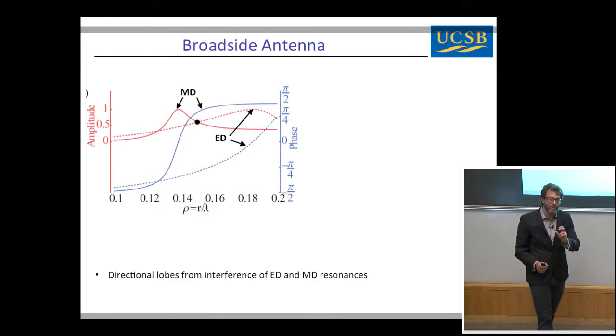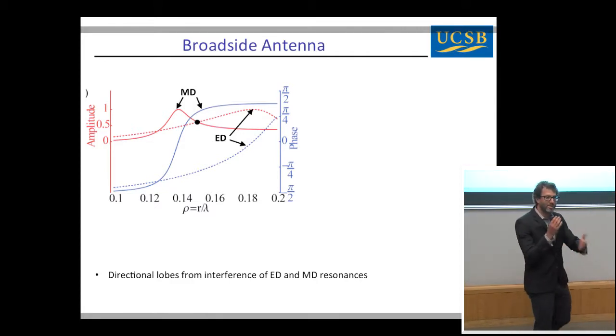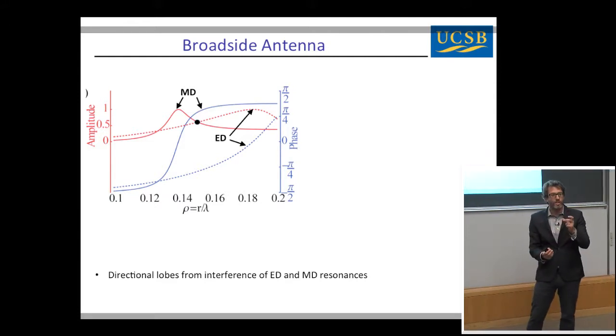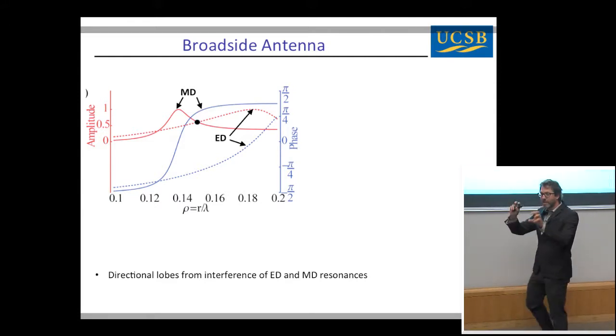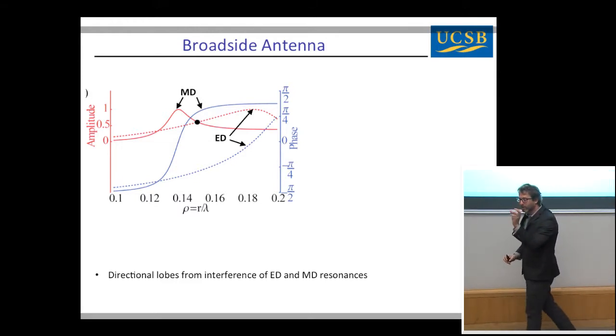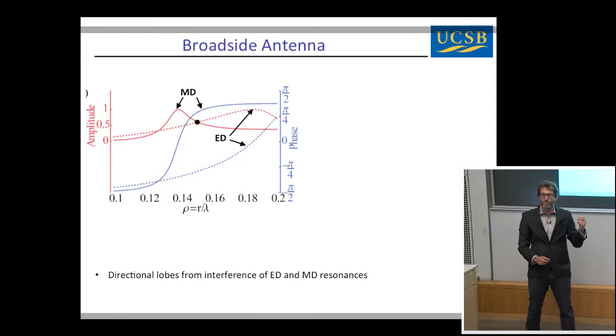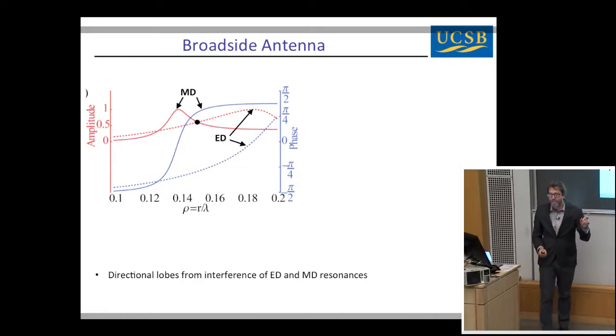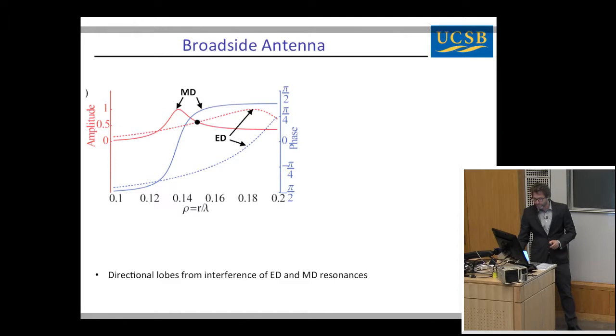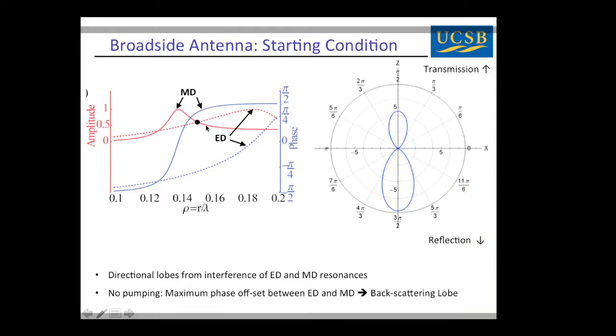Okay? So now what I want to show you is that because of this unique property where we have these different multipole resonances, we can create directional radiation patterns not just by interfering two different particles, but within a single particle by controlling the relationship between these two different modes. Okay? So again, the black dot here is a starting design principle. So we can imagine an unpumped sphere where we design our wavelength to sit right here. So the amplitude of our two modes is equal, but the phase, if we compare the blue curve of our electric dipole mode to the blue curve of magnetic dipole, the phase is at a maximum difference here.